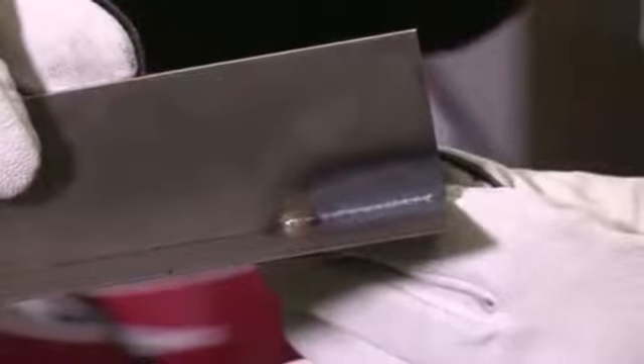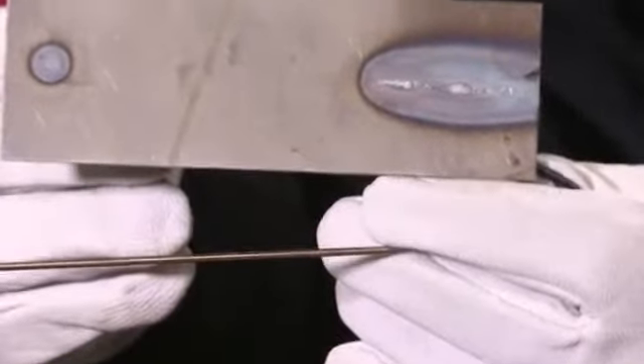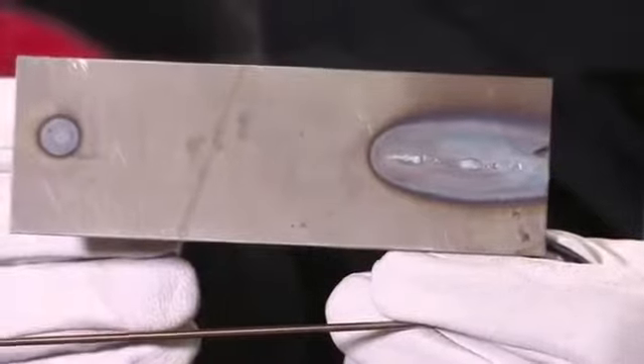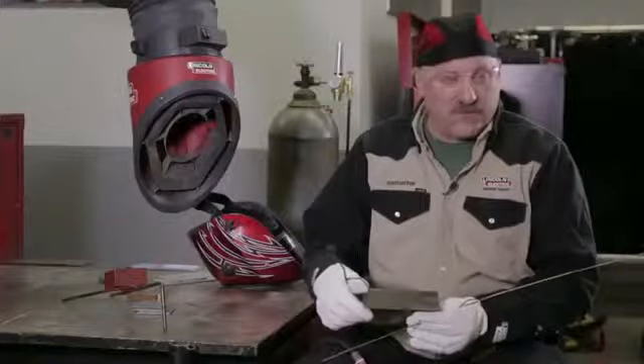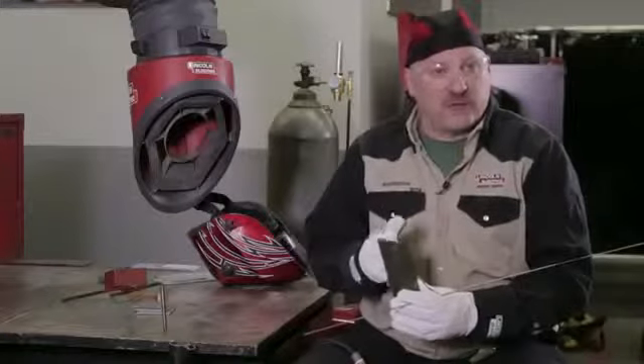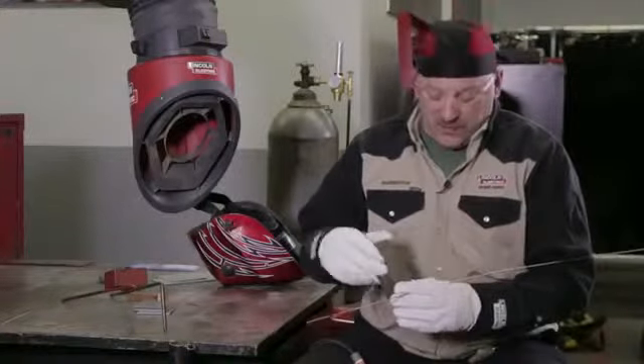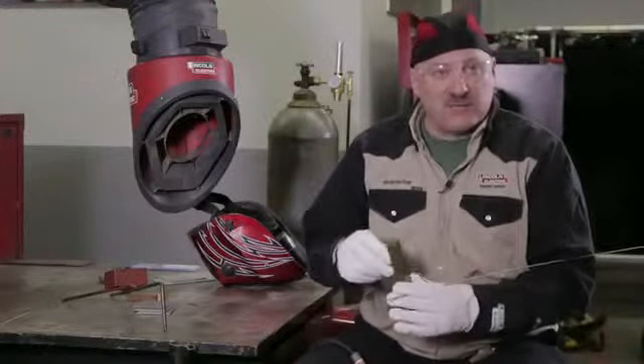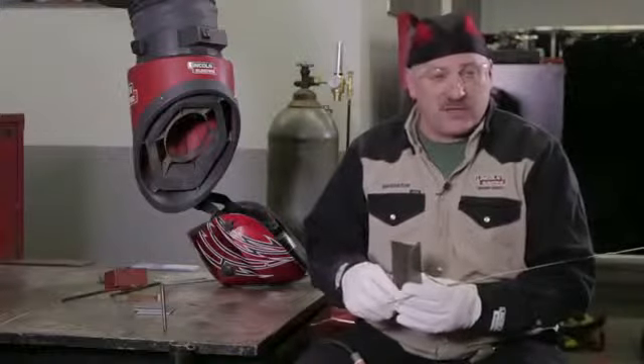And the weld looks pretty good, but if you look at the back side, you can see I have some burn through. And that's sometimes an issue with this. I mean, if you use a pulser, keep your current down low. Sometimes if you're real careful, you can avoid that altogether, but sometimes it's difficult to avoid the burn through on the back side. And if I want to weld a patch on a fender for a car, something real thin, and I don't want this damage on the other side, sometimes brazing is the answer, and you can TIG braze.